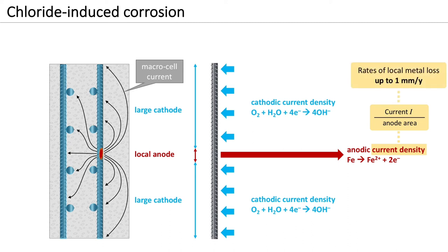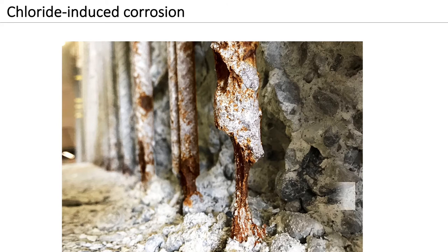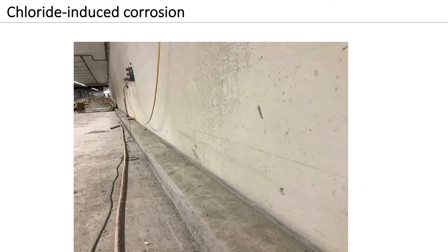In extreme cases, corrosion rates of up to one millimeter per year are possible in chloride induced corrosion. This photograph shows an example of the significant local corrosion attack possible in chloride induced corrosion. Such steel sectional loss may occur without visible signs such as cracks and rust stains appearing at the concrete surface.